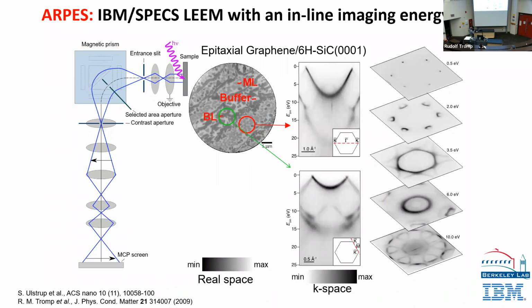Here you see the pi band. Sigma band is down here. And here are the Dirac points, so the singularities in the electronic structure of graphene. If you go to 2 monolayers of graphene, bilayer, you see that this pi band splits up. Can you see that? That this little Dirac point is split up also. There are 2 bands that are just slightly offset relative to one another. Those are the 2 layers interacting with one another. You can do a little better. You can actually create the whole 3-dimensional electron energy versus momentum figure here.